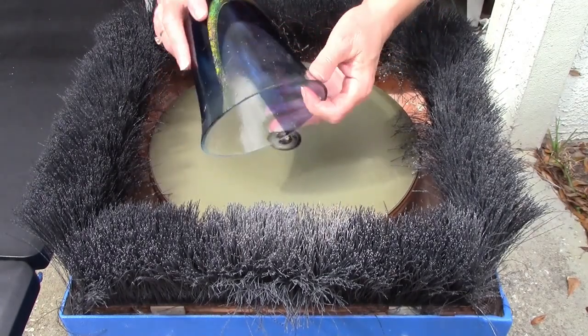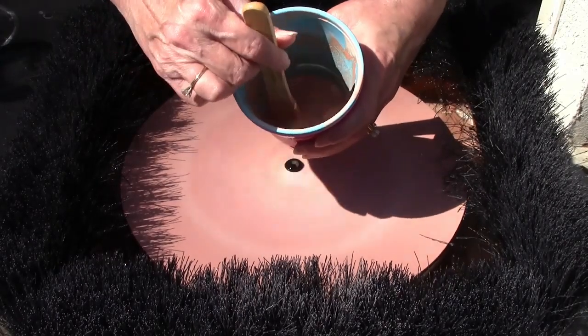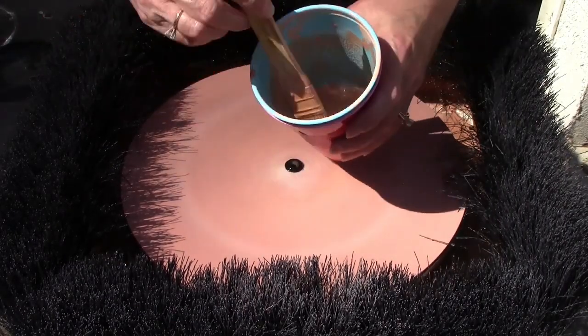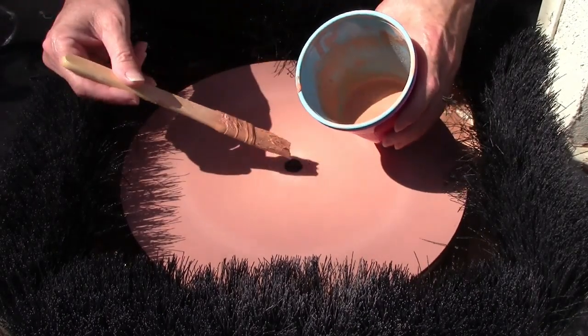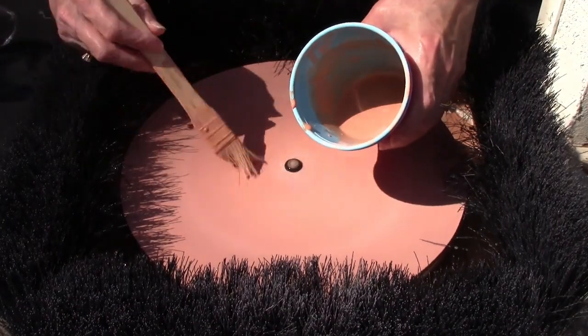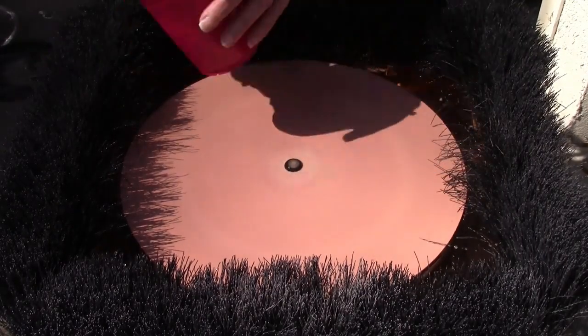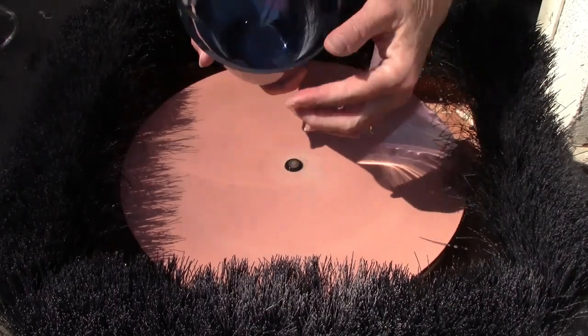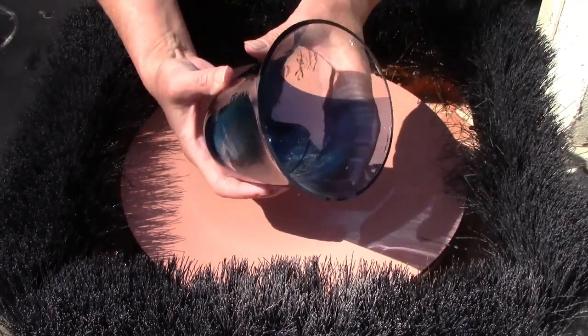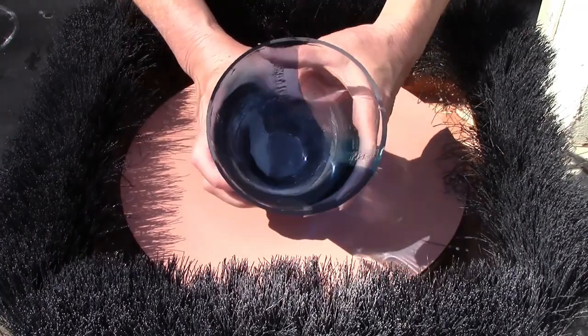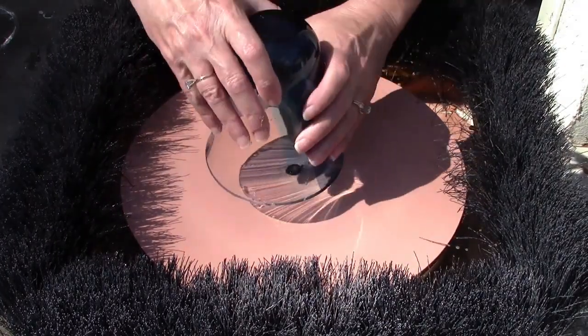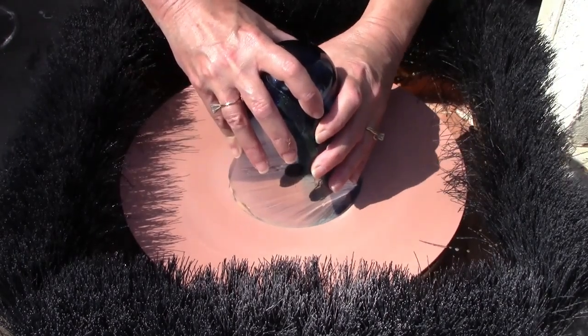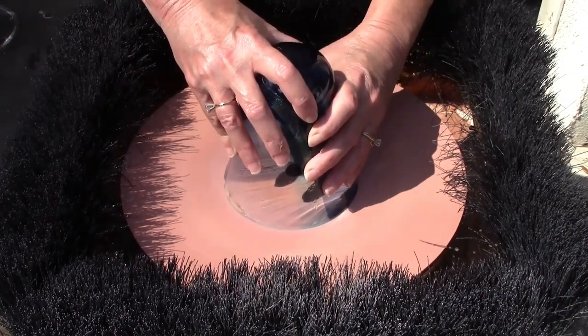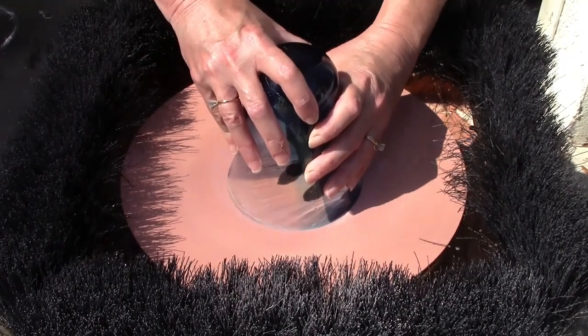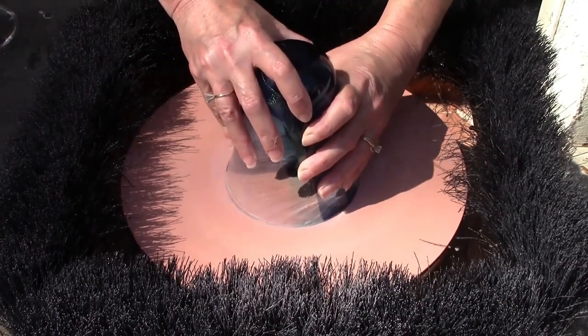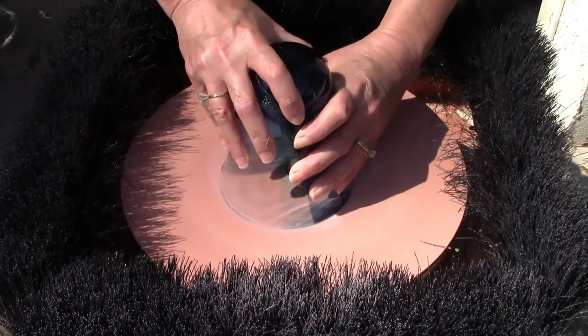Here I'm checking the edge quality, and I've decided it's time to move on to the next step, which is the polishing wheel. This wheel is felt, and I'm using this special medium on top of the wheel to create friction and to shine up that edge, create a polish. So I'm painting this on with a regular natural bristle paintbrush, there we go. And we're going to put this on the wheel. We have a little bit of water there to lubricate it. We want to create a little bit of friction, move this around, and after a few minutes, it'll create a shiny, polished edge that'll reflect the light beautifully and really make this vase very elegant and spectacular.